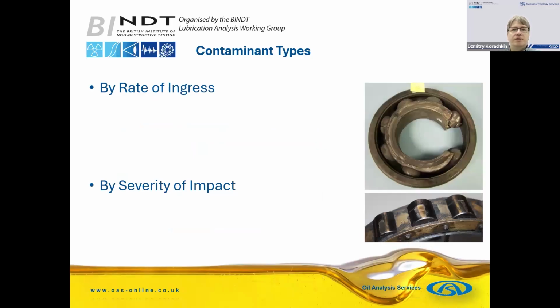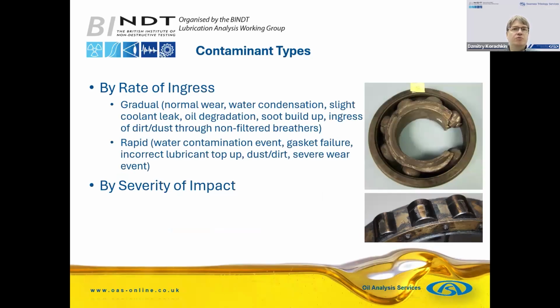We can look at contaminants by rate of ingress. Is it gradual? So normal wear particles, maybe water ingress through condensation, slight coolant leak, the degradation of oil, the buildup of the insolubles, soot buildup, and then ingress of dust and dirt, perhaps through breathers which don't have filtered breathers on, or it could be rapid. So unknown water contamination event, somebody was pressure washing something and lots of water got in straight away, or there's a head gasket failure in an engine, or somebody just put in incorrect lubricants top up, and immediately we have a bulk change, which is very rapid.